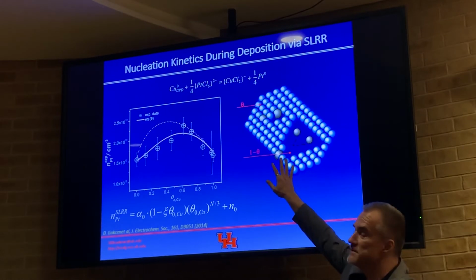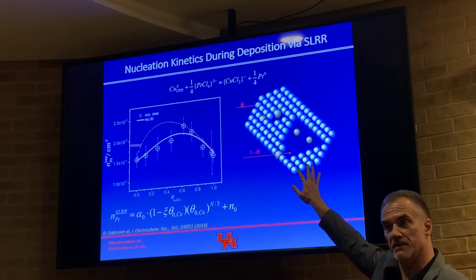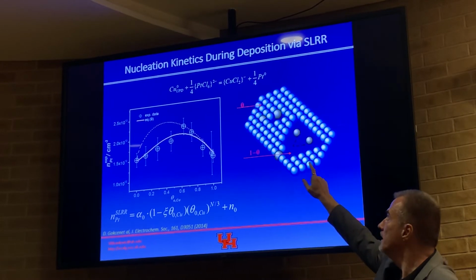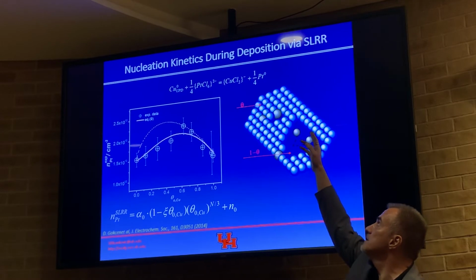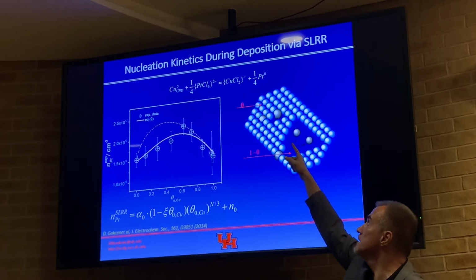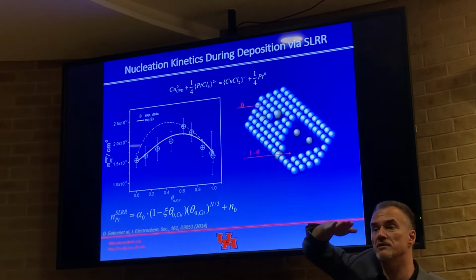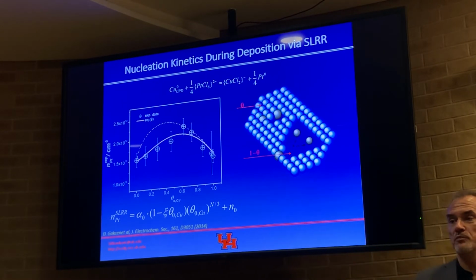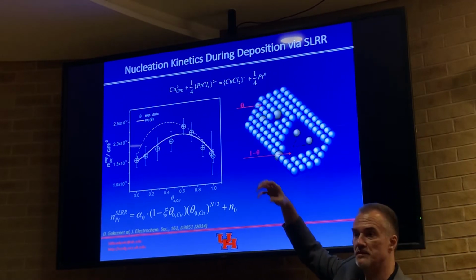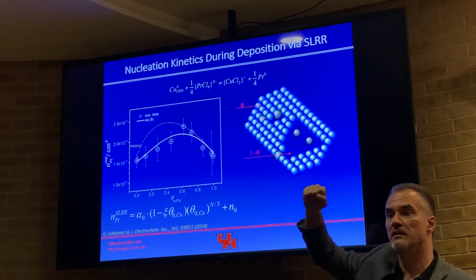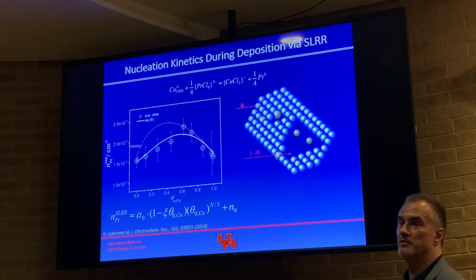But the rest of the surface is covered with UPD atoms that are still there. The platinum atom can actually land not on this portion, but on the other portion which is covered by the UPD. And it can diffuse and eventually incorporate in some kind of a defect site, some missing portion of the UPD, right?